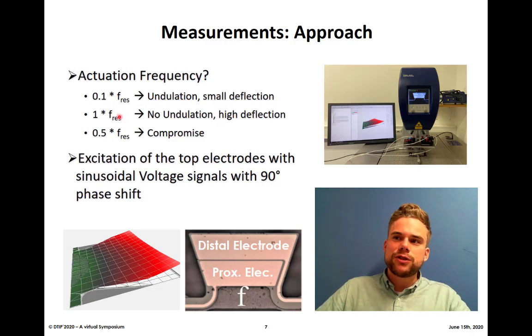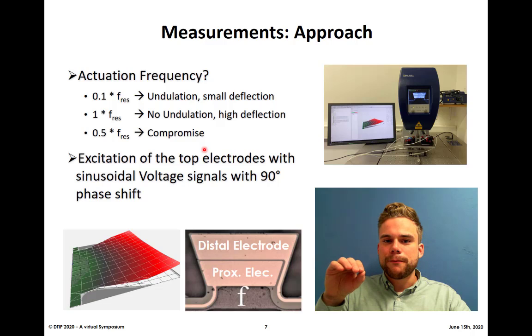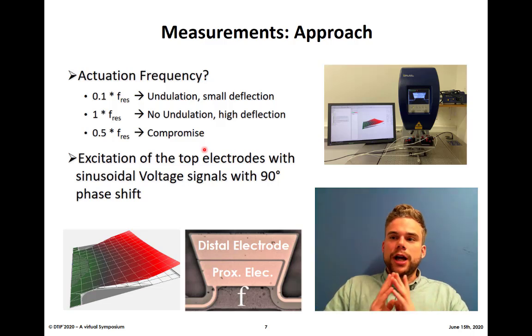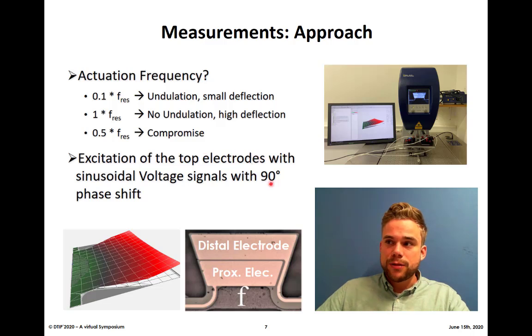So what we did was just actuate with half of the first eigenfrequency as a compromise, to get the trade-off between no undulation but high deflection, and undulation with sufficient deflection. And to do that, we excite the top electrodes with a sinusoidal voltage signal that has a 90-degree phase shift between the two electrodes. And we applied 50-volt peak amplitude for the distal electrode and either 25-volt or 10-volt peak amplitude for the proximal electrode.